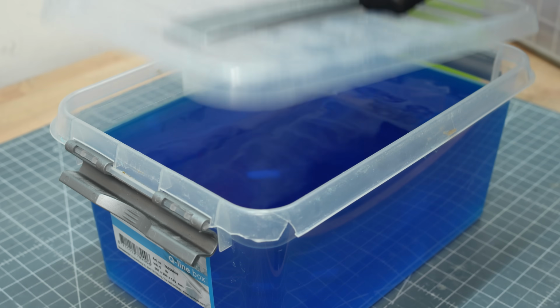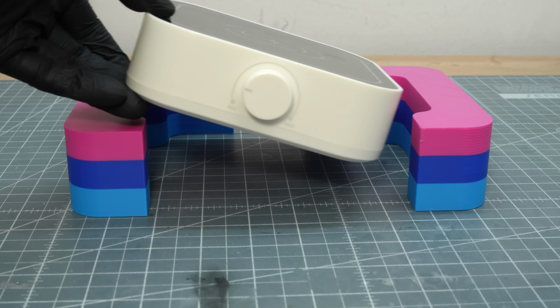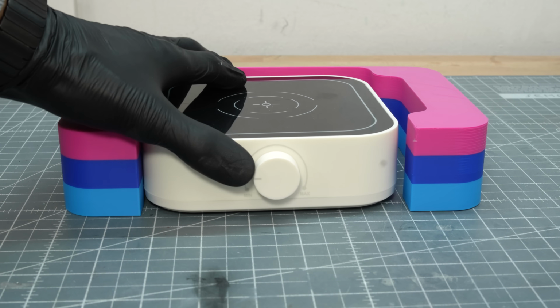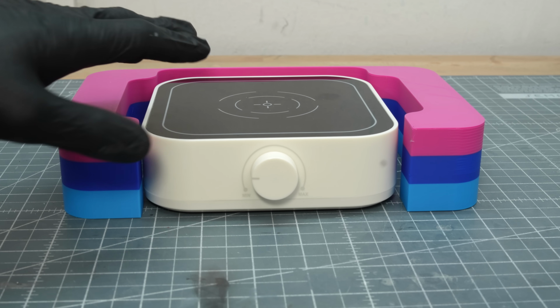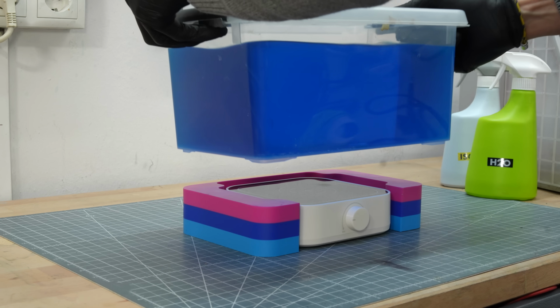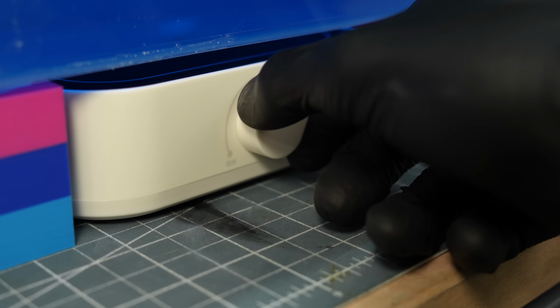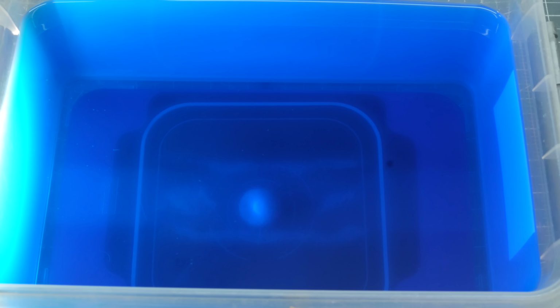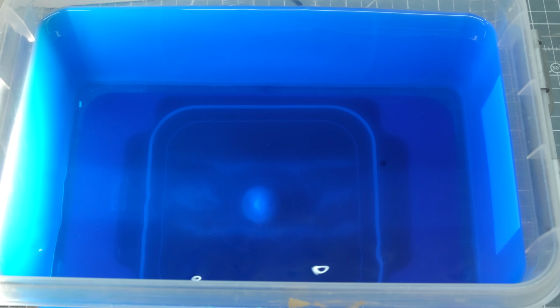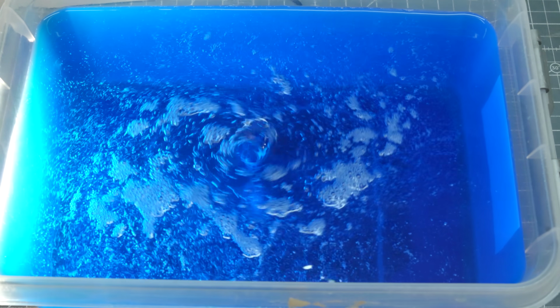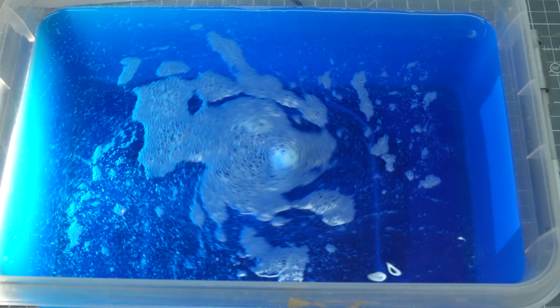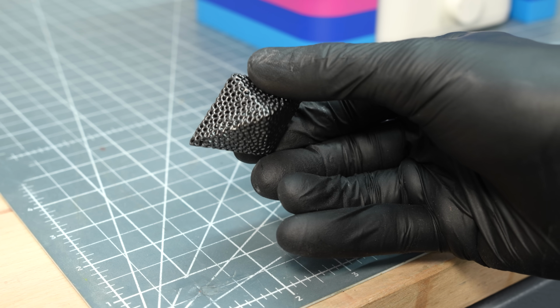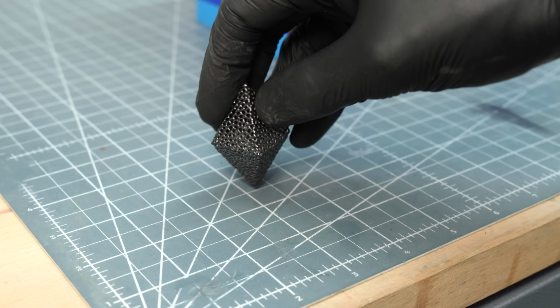So, this is a commercial acidic copper electrolyte which I use to copper plate my conductive prints. Attentive viewers recommended aerating the electroplating bath well to increase the deposition rate. So I built a stirring station. A stirrer keeps the solution moving and improves the deposition rate. Whoops, way too fast. The cool thing about graphite paint is that unlike copper conductive paint, it's quite durable.